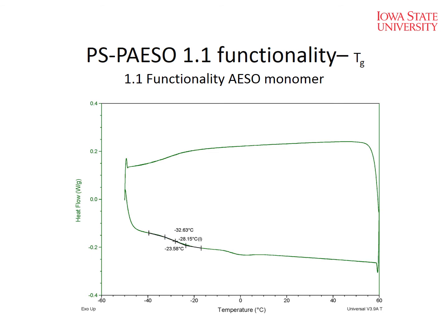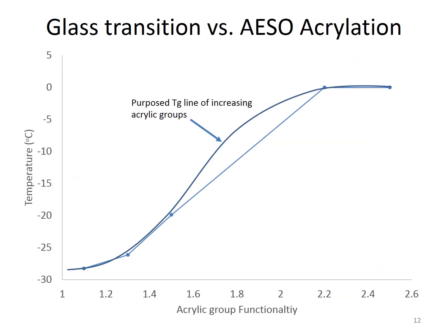Okay, so we can tune these polymers based on end market opportunities and things, right? And so we actually can look at our glass transition as a function of the acrylation, degree of acrylation and their functionality, okay? So this took a fair amount of time to develop, but this helps us understand how to produce these polymers. So if we're at a higher level of functionality, we're going to need to use different solvents than we're used to using in producing polymers. So the one that we've selected when we're up at the 2.5 range, we need methyl THF. Okay? Well, that's a little bit more expensive.